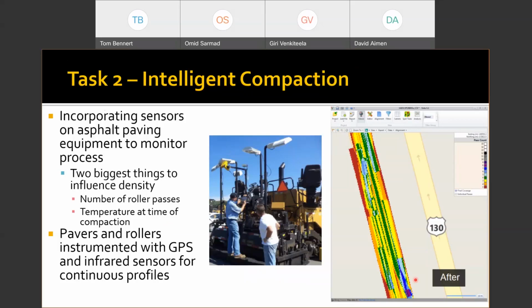The schematic on the right is from a project that we evaluated a couple of years ago under the PSP. You can see we've got different color coding. Red is 1 pass, meaning the roller has gone over it once. Orange is 2, yellow is 3, green is 4, light blue is 5, darker blue is 6. And you can see that for one road, there's really not an even number of passes. In fact, we go from 1 pass over that road all the way up to 6 passes, depending on where we are. The more passes, the more chances you have to better compact the material, and the less likely you're going to get poor in-place material.